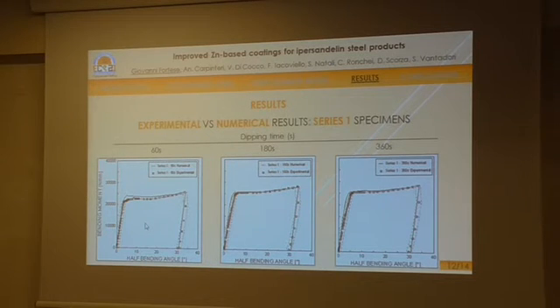As can be observed, a satisfactory agreement between experimental and numerical results is found, especially in the plastic region, which is for half bending angle values greater than about 7 degrees. Dashed lines represent a scatter band equal to plus or minus 1 degree, corresponding to the accuracy of the testing device. For high values of half bending angle, an increase in strength is observed by increasing the dipping time.